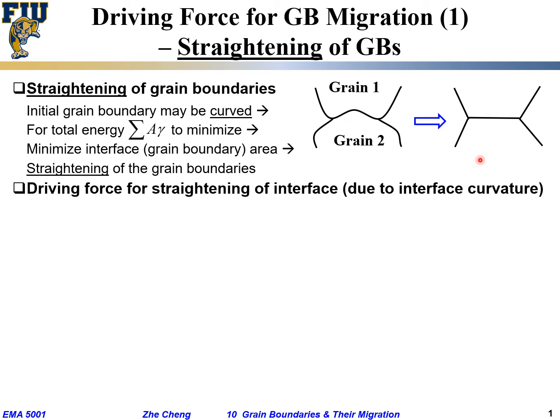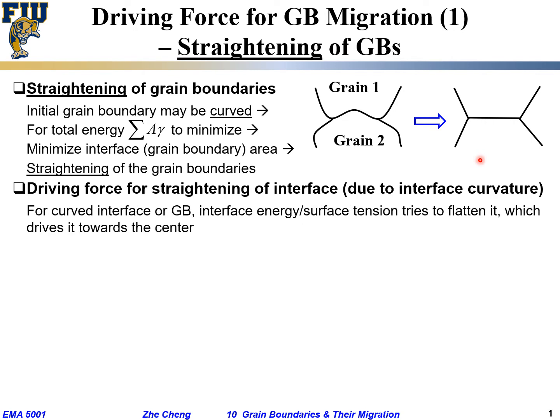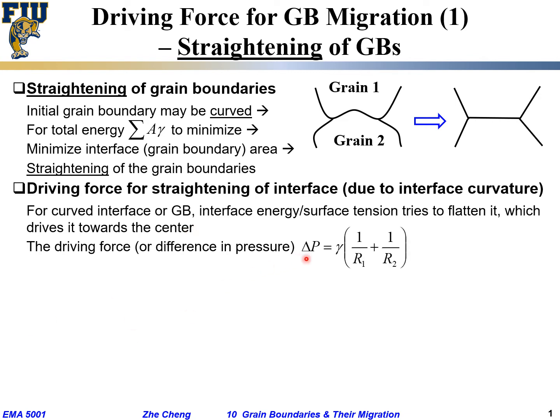The driving force for this straightening of the interface — in this case, the grain boundary — is related to what we learned in physics for a curved surface: surface tension. The energy tries to make the curved surface flatten, driving the curve towards its center. When the curve becomes infinitely flat, the radius of curvature becomes infinity. In physics, delta P — the pressure difference across a curved surface or interface — equals gamma times (1/r1 + 1/r2).